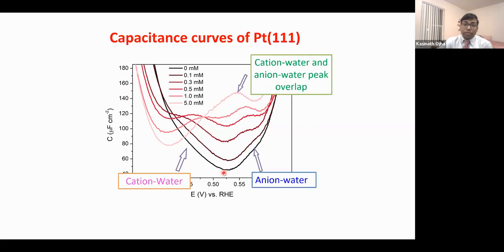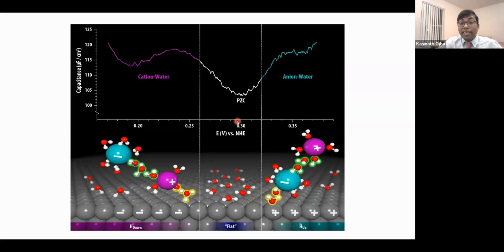And if we do more studies on different ions, different concentrations, different conditions, what we found is those regions actually depend on cation-water interactions, and those regions depend on anion-water interactions. And those two are merging together at high concentration, moving together, and at high concentration, instead of a minimum, you see a peak, because those two are merging together. And there is a clear schematic.